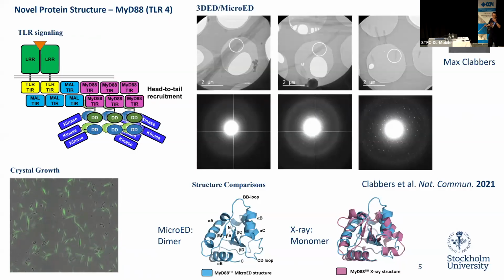And the problem they had is that when they collected the diffraction data from these crystals, it was very difficult to index them. Until we put these crystals into the microscope, we realized that these thin crystals actually bundle together. They form like a stack of thin needle crystals. So the diffraction pattern you get from these crystals will be very difficult to index because they came from multiple crystals. But with the capability of doing imaging in a microscope, we can look for single crystals and then collect the rotation 3D data from these single crystals. And then those crystals actually diffracted beautifully.